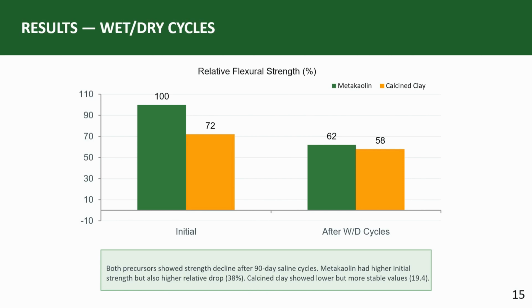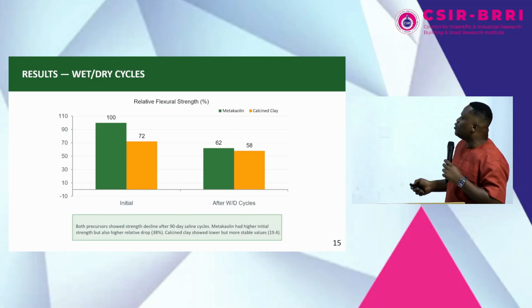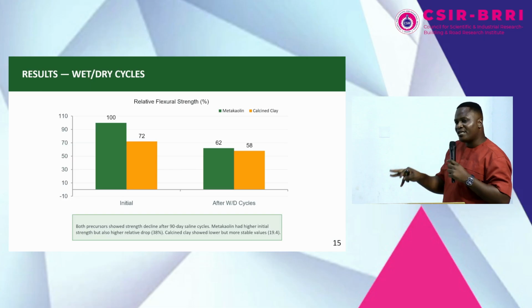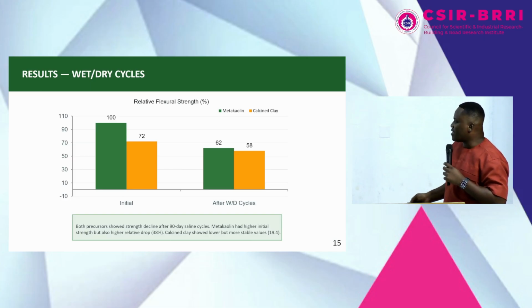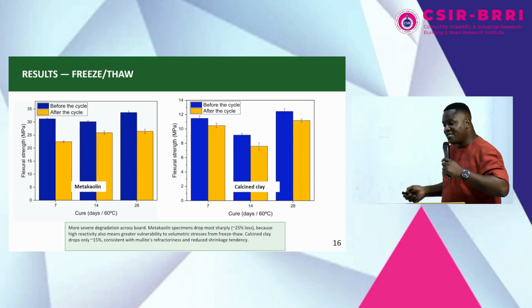You realize that this is the initial result, assuming it is 100, the initial result for the metakaolin, because we are comparing the calcined clay with the metakaolin. So the metakaolin, if it is 100, the calcined clay initially is performing around 72%. But after the 90-day period, you realize that the difference between the metakaolin and the calcined clay is not that much. If you even do the calculation, the metakaolin is losing 38% of its strength after it has been subjected to that sodium chloride environment. However, the calcined clay, even though the strength was low, is more stable and lost only 19.4% of its strength.